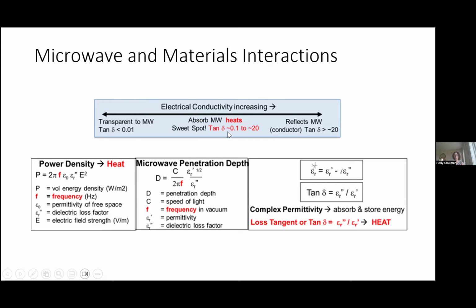And I've put down tan delta about 0.1 here. Really, it's less than that. It's probably about 0.02, and it kind of depends on the material. And this is thinking with 2.45 gigahertz, but this is really a rule of thumb, kind of trying to give the understanding that there's a range, and there's a place where dielectric materials can really absorb well.